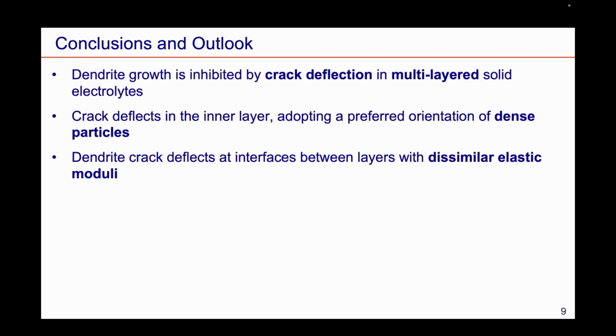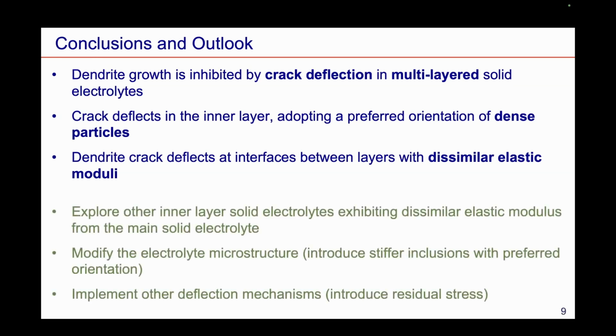So we can conclude that the dendrite growth can be inhibited by the multi-layer solid electrolyte structure, and the crack can deflect along the interface between layers with dissimilar elastic moduli, and the crack can also be deflected within the inner layer, which adopts a preferred orientation of dense particles. So these findings inspire further exploration of fracture-tolerant solid electrolytes by exploring other inner layer materials which exhibit dissimilar elastic moduli from the main solid electrolyte, and modifying the electrolyte microstructure by introducing stiffer inclusions with preferred orientation. Other deflection mechanisms, such as introducing residual stress within the solid electrolyte, can also be adopted.